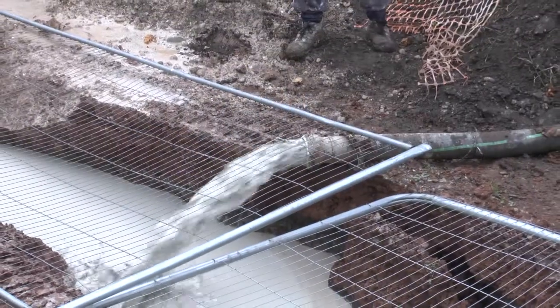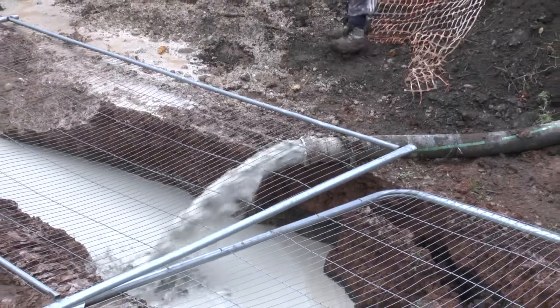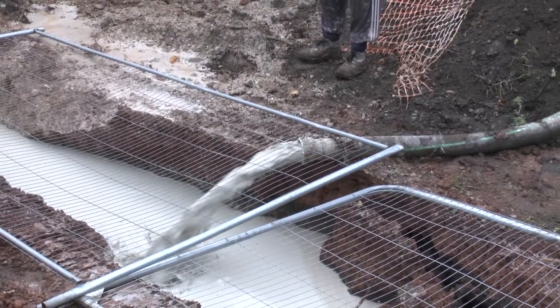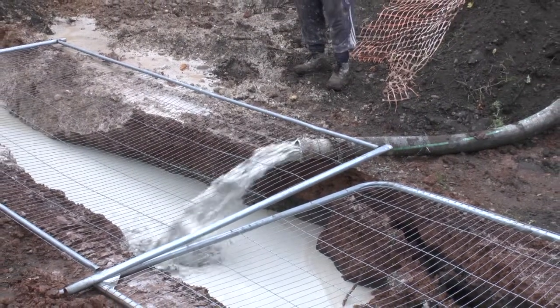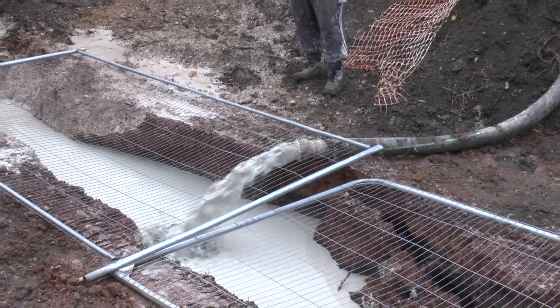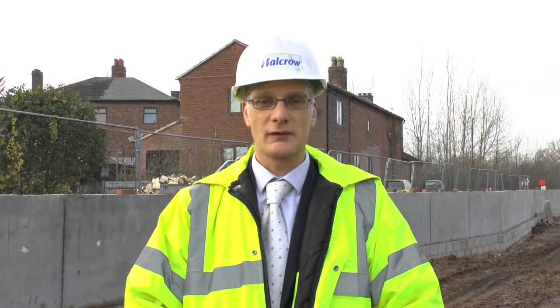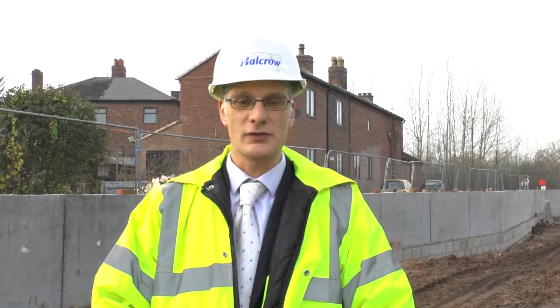We started to look at bentonite as a solution to the problem. This appeared to meet all our requirements. It was cheap, easy to install, had a relatively low carbon footprint compared to the other solutions, and most of all it had very low vibration levels during installation, so minimised the risk of damage to the adjacent properties. There was an added health and safety benefit in that the bentonite is easy to trim down to formation level, so it avoids needing to cut steel or break down concrete piles.